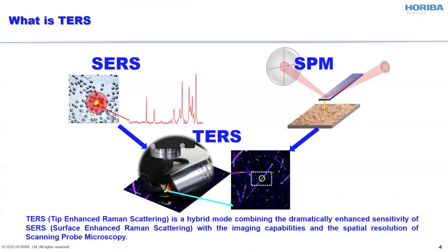Okay, so tip-enhanced Raman scattering, or briefly TERS, is a combined technique that integrates the advantages of surface-enhanced Raman scattering and scanning probe microscopy in a way that when we place a plasmonic structure at the apex of the SPM probe and illuminate the structure with an external laser, both the incoming field and the scattered field get greatly enhanced by the plasmonic structure that serves as a nano antenna that confines the field into a nanoscale volume, thus enhancing sensitivity and, even more importantly, the spatial resolution of Raman imaging, which becomes comparable or sometimes even better than the spatial resolution provided by the corresponding scanning probe microscopy technique.